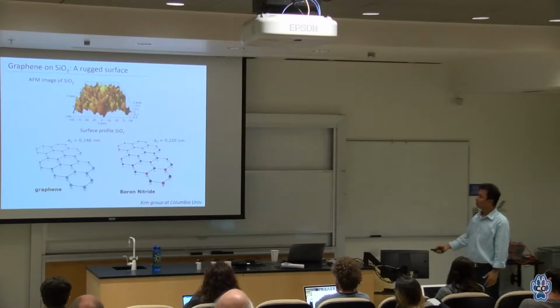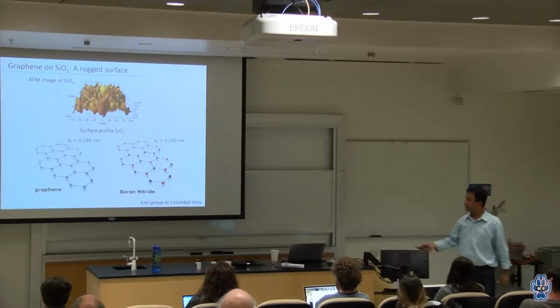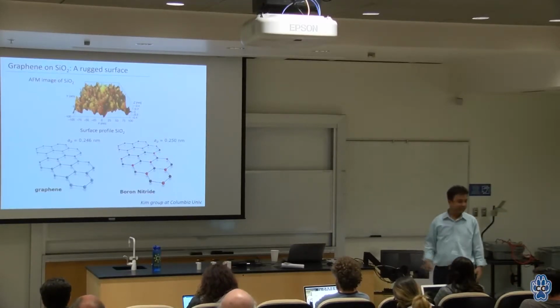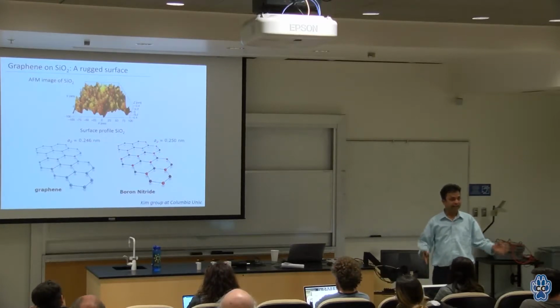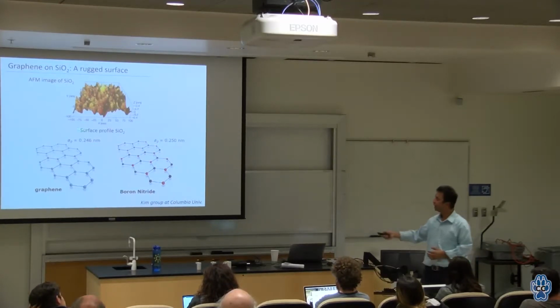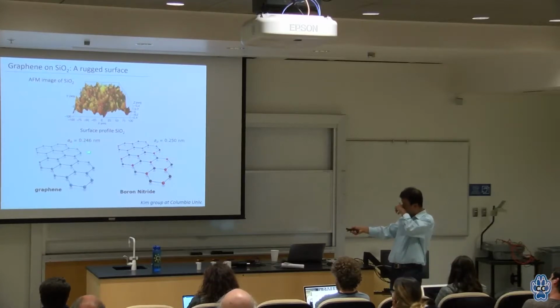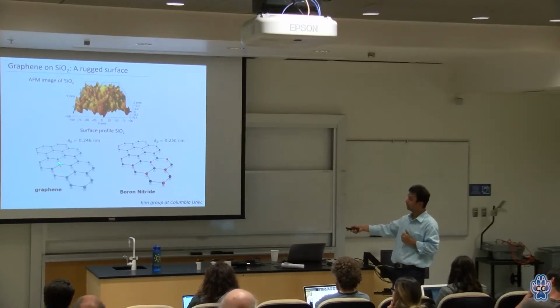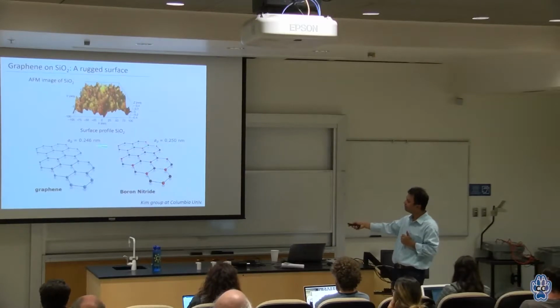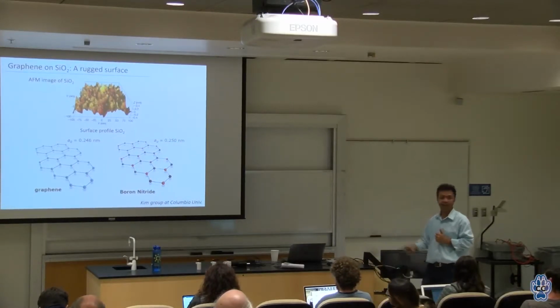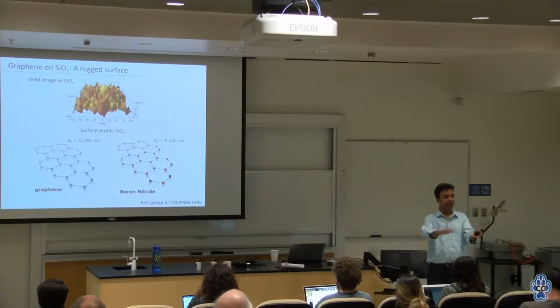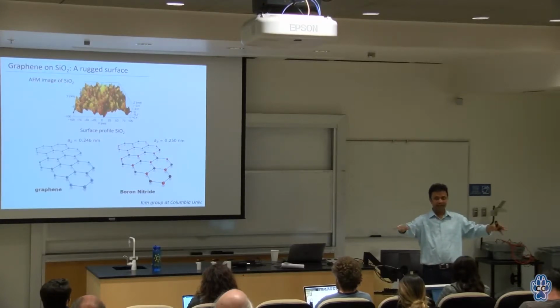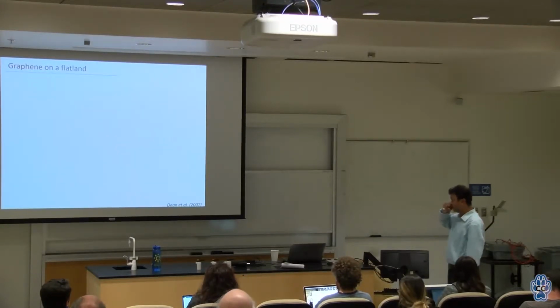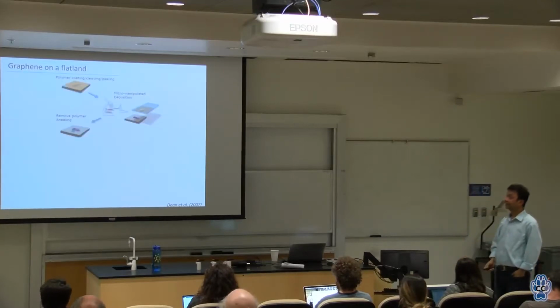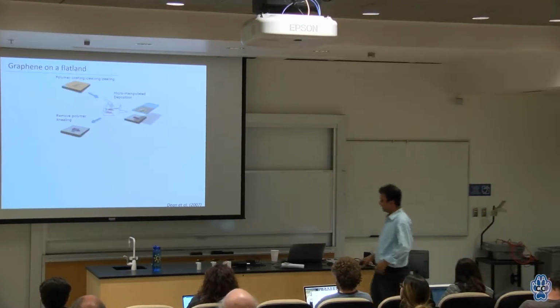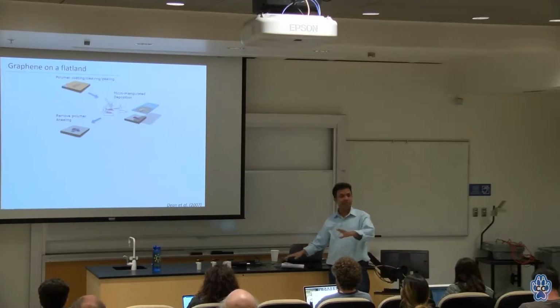All right? So what we found, well, you have graphene here, and you have a brother here called boron nitride. It's exactly the same structure. The lattice constant, the separation between the atoms, is very close to this boron nitride. And this is also a layered material, so you can have an atomically flat substrate. So that is what they did. This is the next advancement they did.